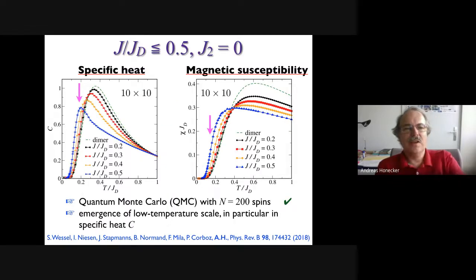Good. Here, I'm showing you some results that are obtained with the method. On the left-hand side, you see the specific heat. On the right-hand side, you see the magnetic susceptibility. These are quantum Monte Carlo results for an effective system of 200 spins. And the first message is that you get very clean data up to a ratio of 0.5. So quantum Monte Carlo works, you get nice results on big system sizes. And from the physics point of view, you see that there's a nose emerging in the specific heat corresponding to the edge in the susceptibility on the right-hand side, meaning that you get the emergence of a low energy scale in the thermodynamics if you crank up the interdimer coupling.